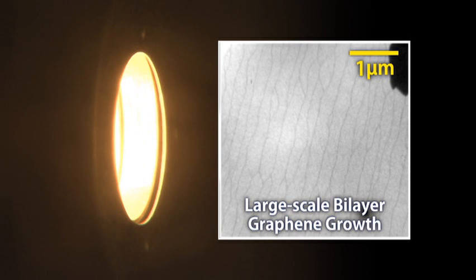In this way, we have been able to grow uniform two-layer graphene films over areas up to several micrometers in size by controlling growth.